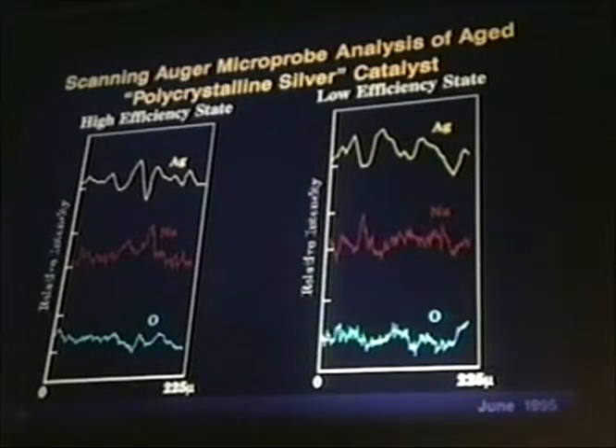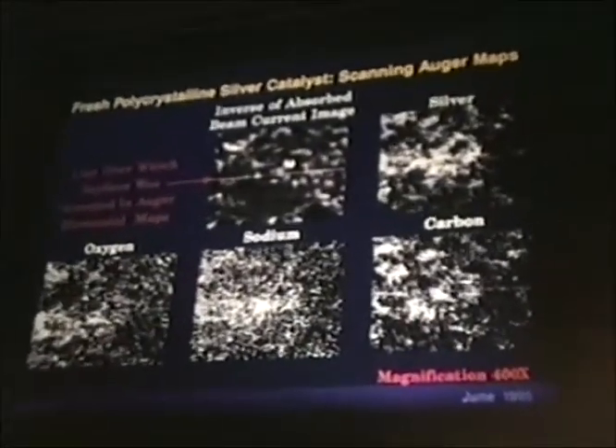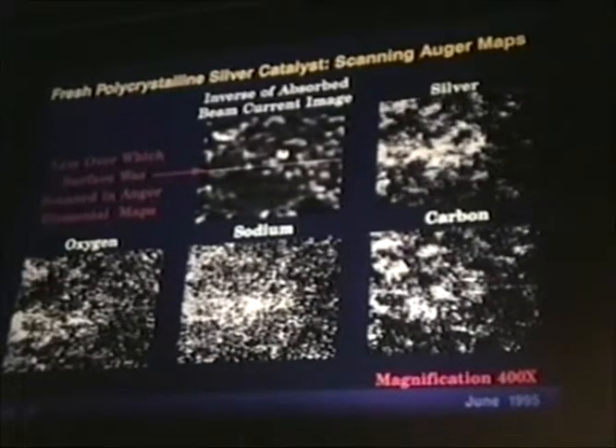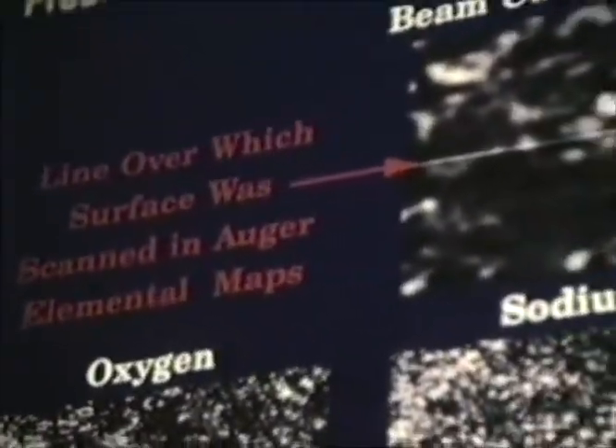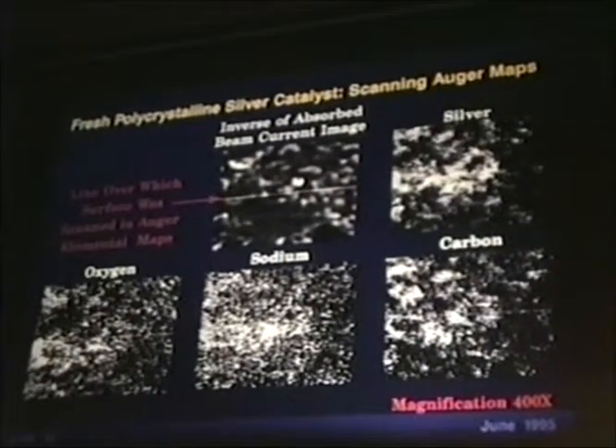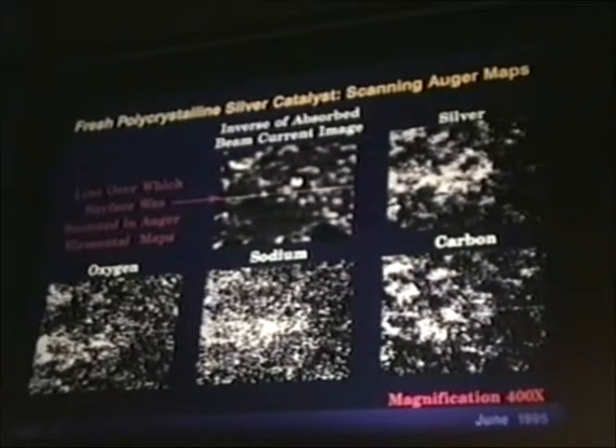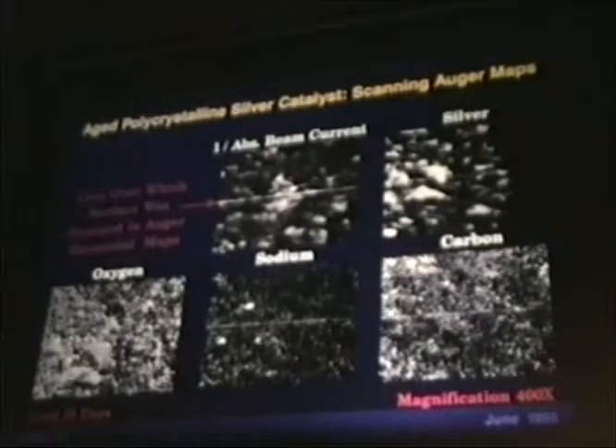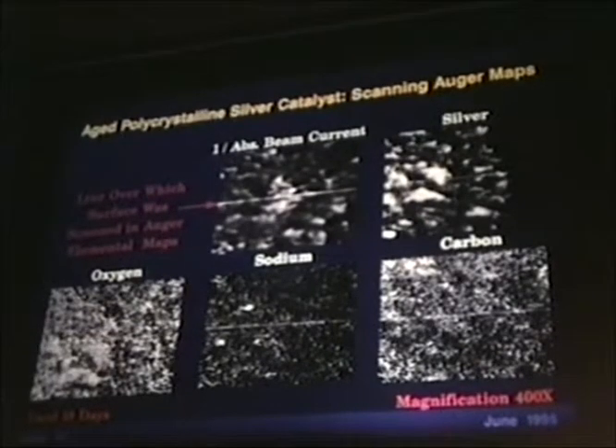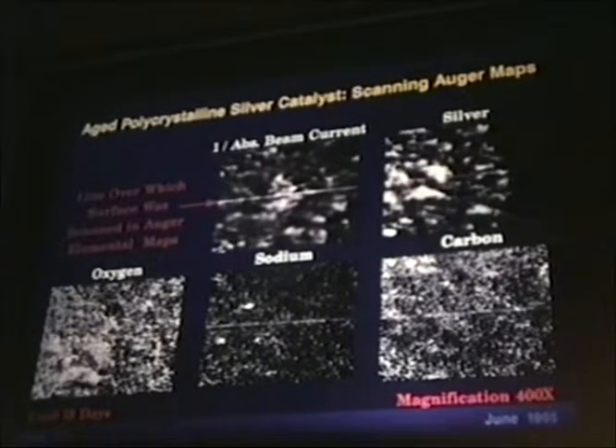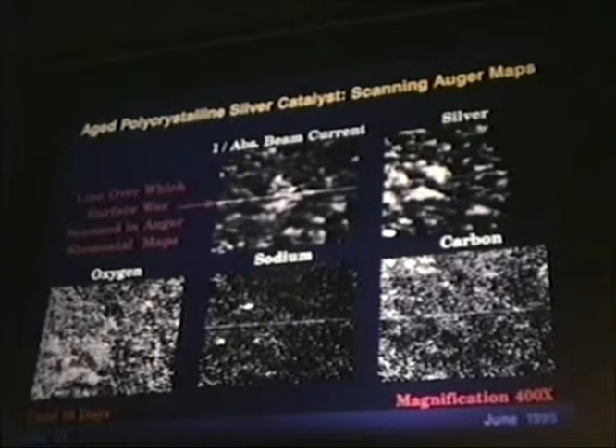And in addition, in the next slide, two slides, we did both the SEM and the scanning Auger maps of silver, sodium, oxygen, and carbon. Particularly noteworthy is silver and sodium, and as you can see in the fresh state of this polycrystalline silver, sodium is very evenly distributed in the map. Next one. This is the one where I showed you the line scans to be not matching with the intensity and hence aged.